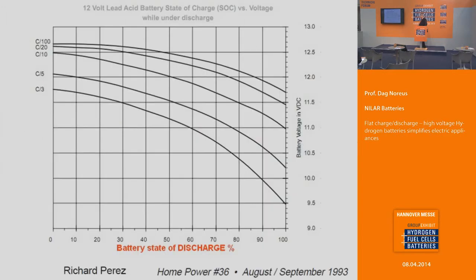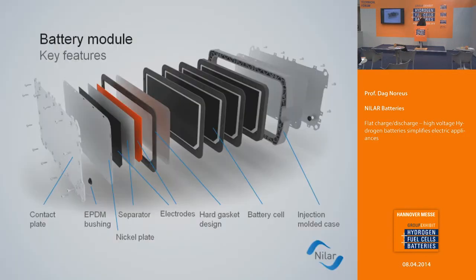And the lead acid battery is sort of the main one. This is the discharge curve of a lead acid battery. It's rather sloping and not so high. If you try to drain it at a higher discharge rate, the slope increases. So what you can do here, if you have this flat discharge curve and you have control of the overcharge and over-discharge reactions, then you can combine cells into modules. And this is sort of the main benefit of the NILAR battery that is presented here.